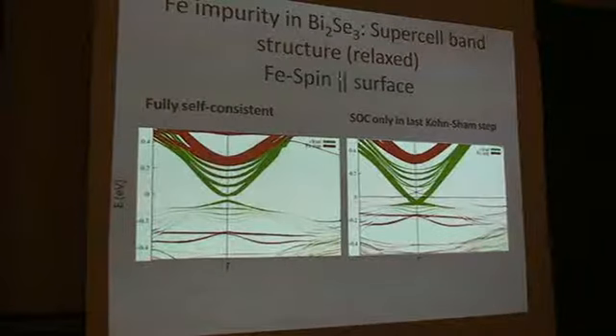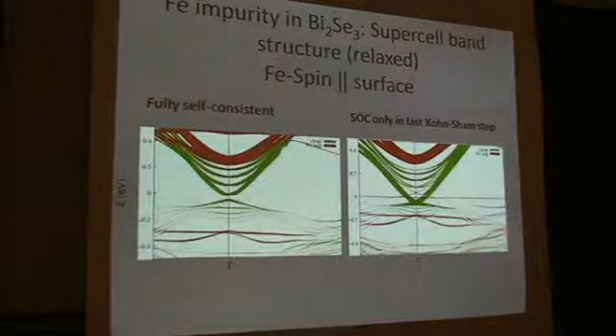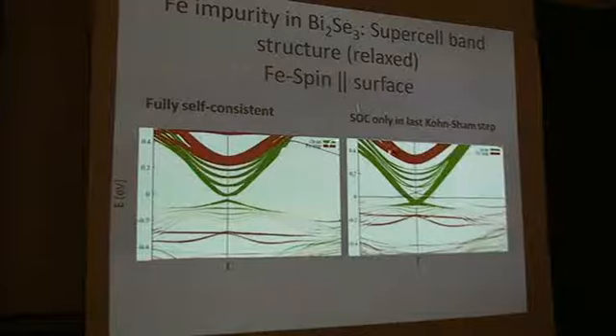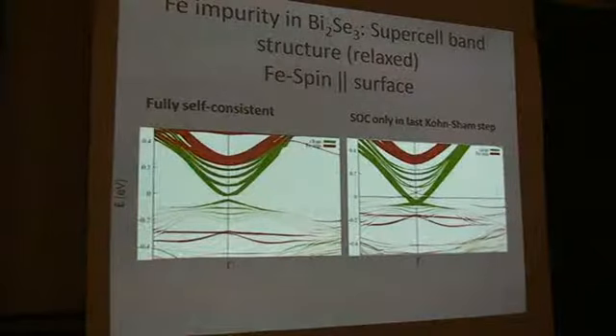So I can look at the iron impurities, the 4 of them on the top layer, which I can line up out of the plane, or I can put them all in the plane. So let me show you first a calculation where iron spins are all parallel to the surface, and therefore they should not have any effect as far as the gap opening. And indeed they don't. What you see is that you can do the fully self-consistent solution in the presence of spin-orbit coupling. This gap here is actually the gap because of the numerical calculation. It's a finite system, and so this is actually not significant. This is not the gap due to the additional iron. This gap would be present even for the pure bismuth selenium.